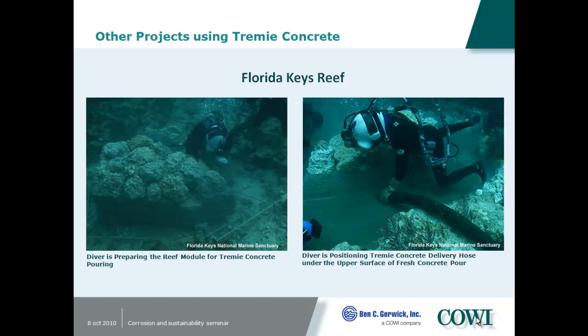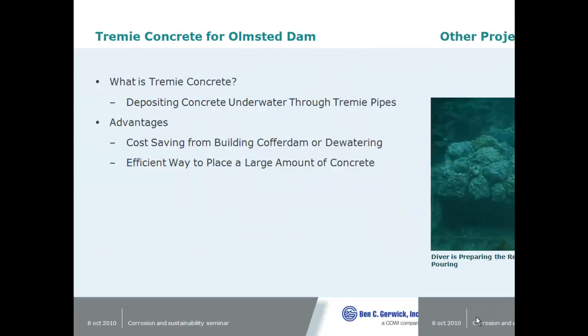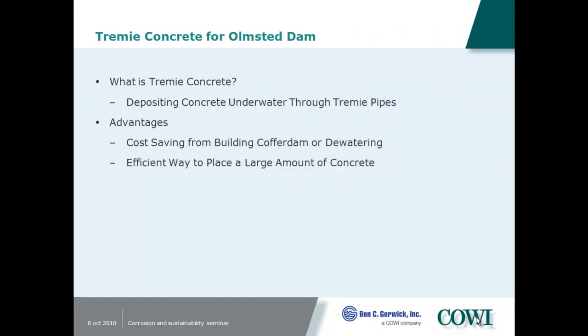So we made precast concrete elements and some rock boulders, and then used anti-washout admixture with the Tremie concrete. Well, it was almost a 12-inch slump concrete. It was self-consolidating concrete. And there was no negative impact on the surrounding fish or the lobsters that were down in there. The anti-washout admixture stops the cement particles from going off into the water, making it alkaline.